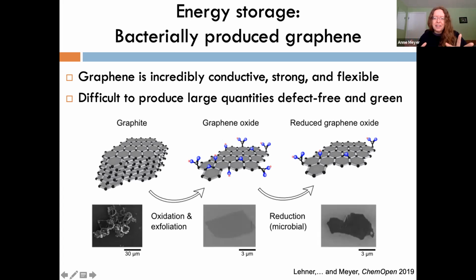So basically you start with graphite, pencil lead, so to speak. You take your graphite, you oxidize it to graphene oxide, then you have very thin layers of graphene, but they're covered in oxygen molecules. And then you reduce it, and the more you can reduce it, the more graphene-like your material becomes, right? So this is the way to get very thin layers of graphene that's almost pristine, so very few side groups on it. The problem for us is that both of these steps are very energy intensive and produce a lot of chemical waste, right? And for the second step, to make reduced graphene oxide, one way you can do that is you heat it up to 1,000 degrees Celsius for 24 hours, which is not very energy efficient.